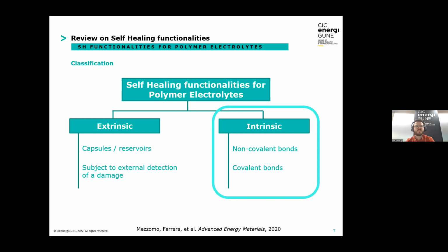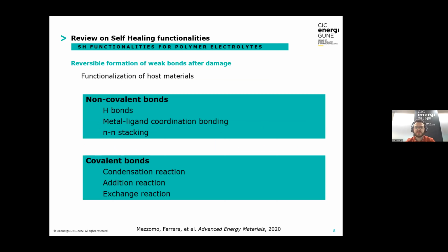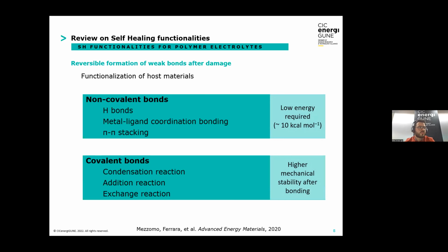So within intrinsic self-healing, we have non-covalent and covalent bonds, and here I gather different examples of self-healing through these two types of bonding. For non-covalent bonds, self-healing includes a wide variety of chemical interactions that can generally be grouped under supramolecular dynamic chemistry, and it requires a lower energy to be activated compared to covalent bonds. For non-covalent bonds it is around 10 kilocalories per mole, whereas covalent bonds require a higher energy, and healing through covalent bonds also leads to a higher mechanical stability.